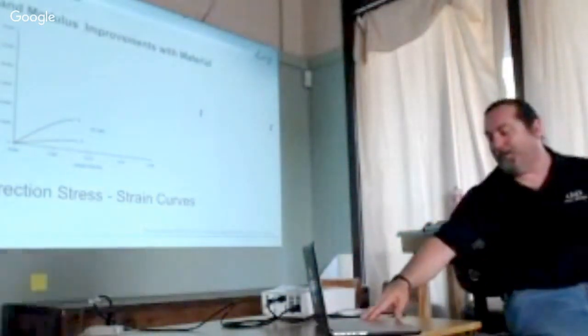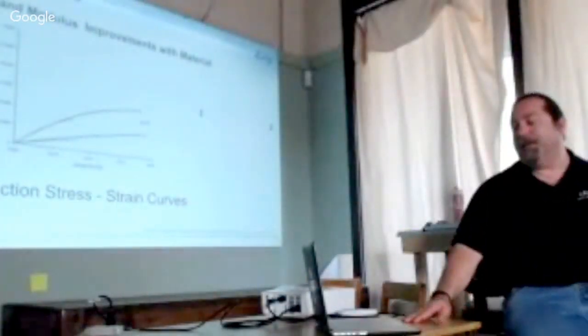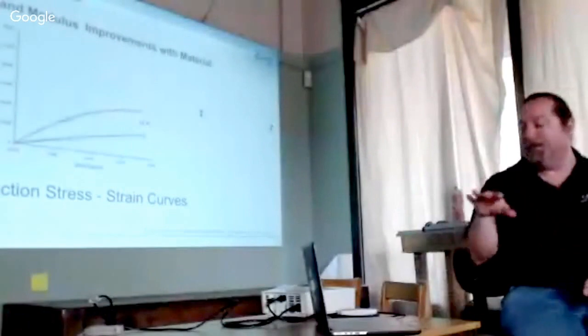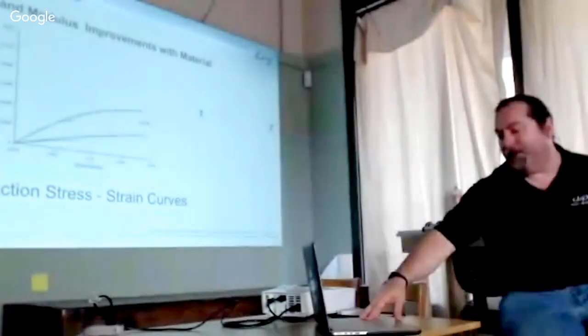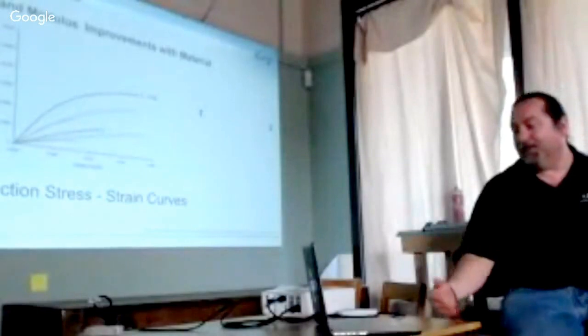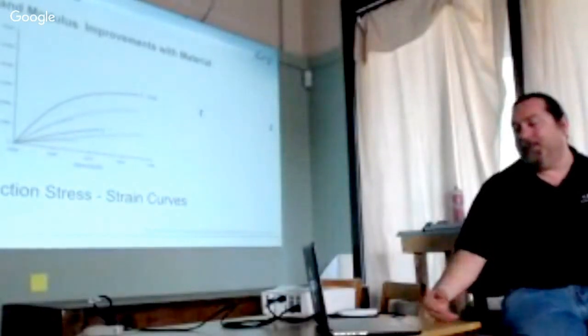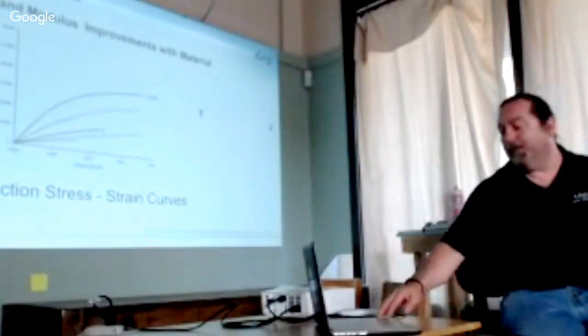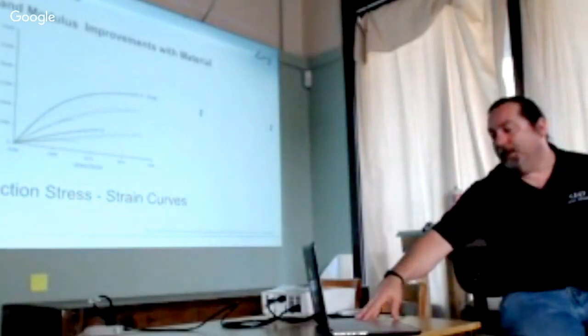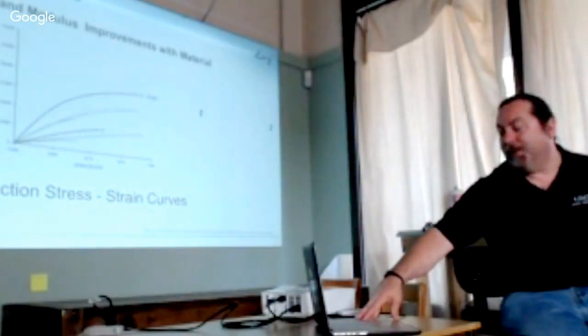This is the stress strain curve for the original carbon fiber ABS material. And then here's the carbon fiber polycarbonate. It has about the same stiffness, but double the strength, so it gets a higher strain to failure. Then this is a nylon that prints well, and it's about twice the strength of the carbon fiber ABS, or 2.5 times.